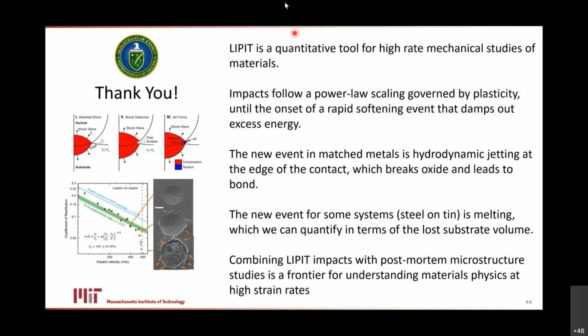No, so I apologize if that went by too fast, but basically it's a mismatch, right? We know directly from measurement that we've ejected 800 cubic microns of matter. So we know exactly how much matter we've ejected. Then from a separate measurement, we know how much energy was available to do melting in those experiments, and the energy available could only melt 30 cubic microns. So we're ejecting 800, but there's not enough energy to melt more than 30. QED, right? Most of it could not have been melted. Most of it had to be solid.